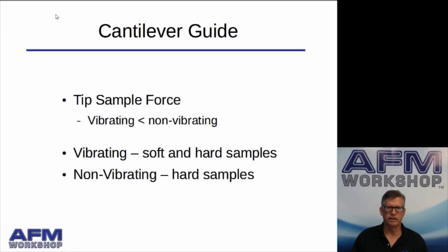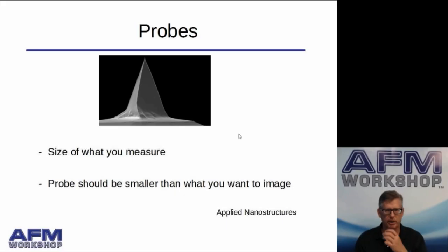So for cantilevers, here's a general rule. The tip sample forces are less for vibrating mode than non-vibrating mode. What that means is for vibrating mode, you can use that on soft samples and hard samples. Non-vibrating probe or contact mode is typically used on hard samples. So in AFM Workshop, we almost always do our scanning in vibrating mode because that works for both soft and hard samples.